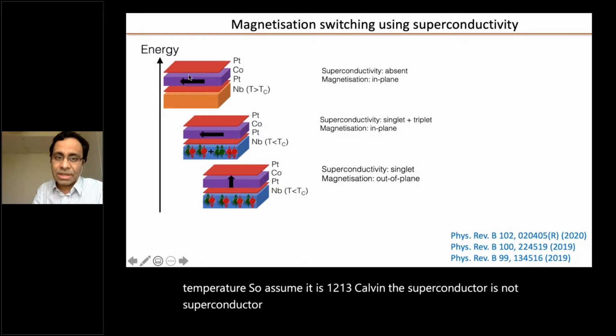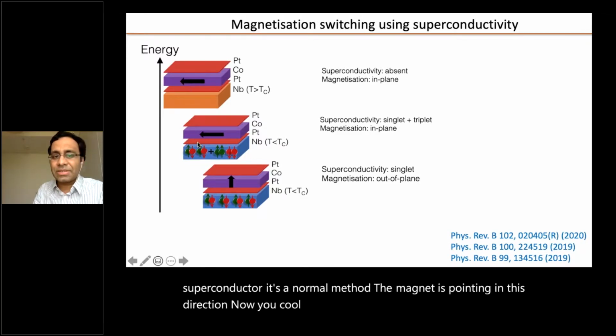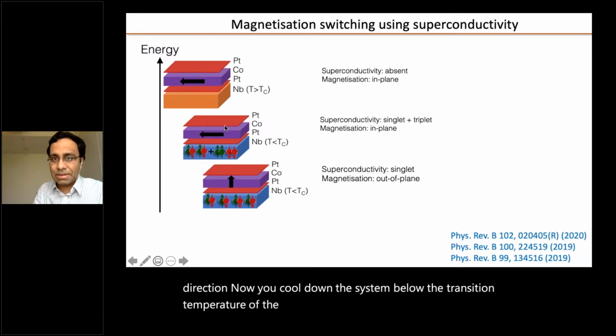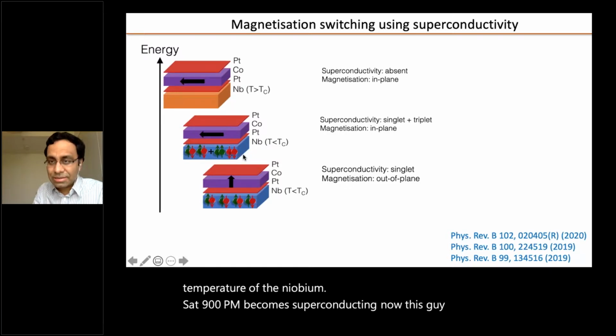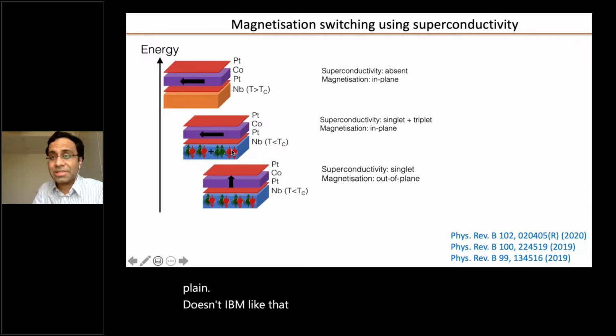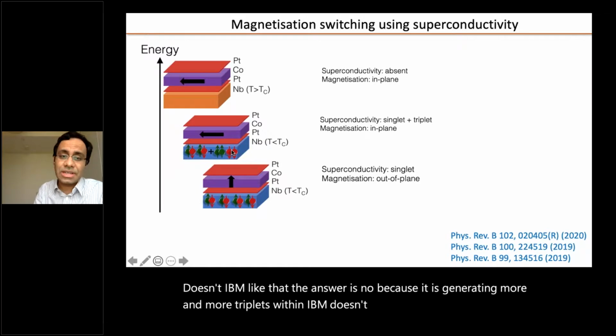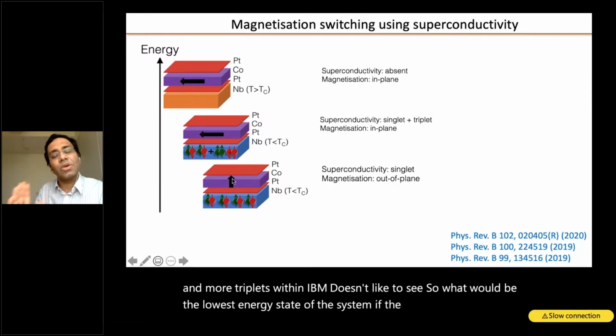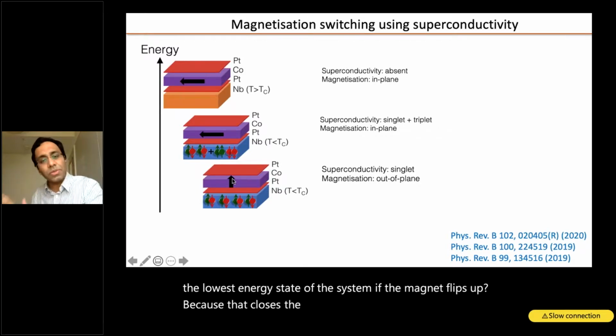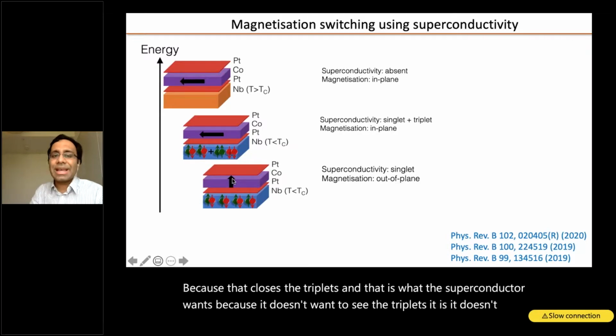Now you cool down the system below the transition temperature of the niobium. So the niobium becomes superconducting. Now this guy is still pointing in plane. Does the niobium like that? The answer is no, because it is generating more and more triplets, which the niobium doesn't like to see. So what would be the lowest energy state of the system if the magnet flips up? Because that closes the triplet channel. That is what the superconductor wants, because it doesn't want to see the triplets. It doesn't like the triplets.